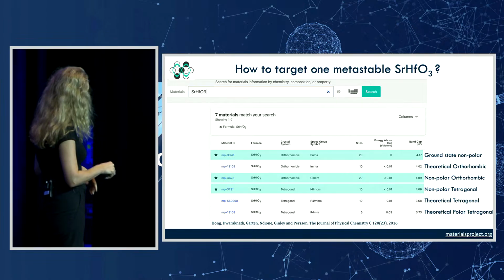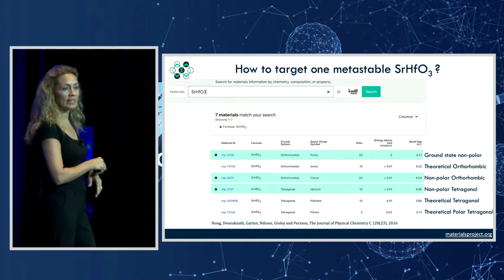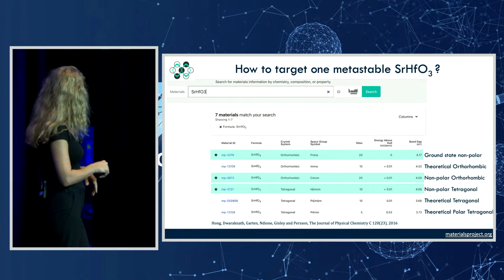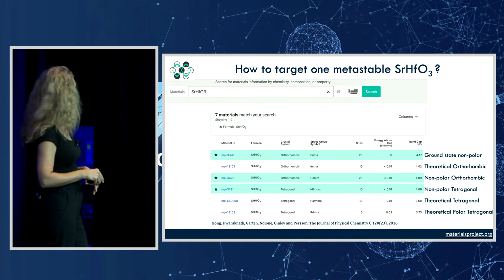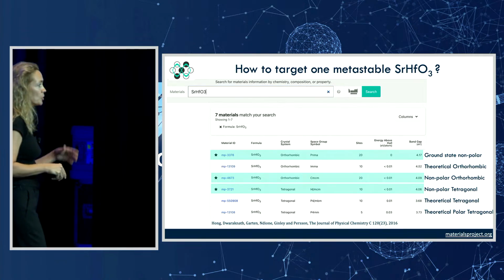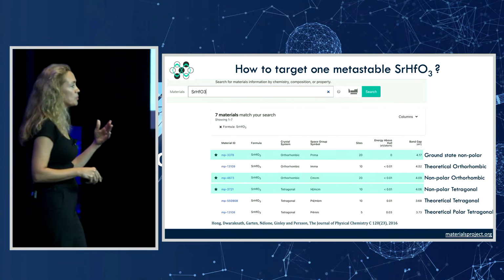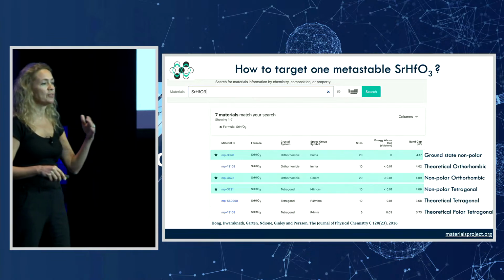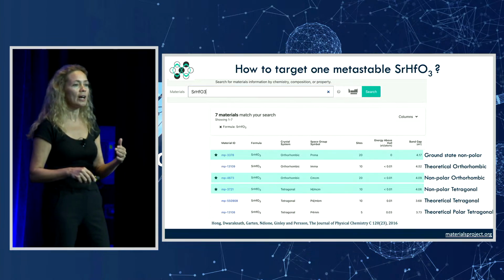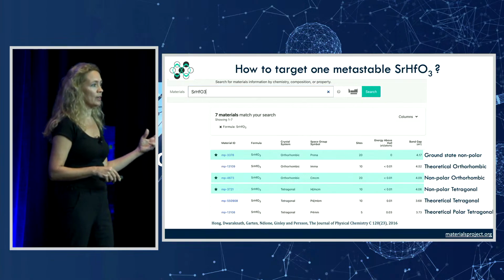It's the only one that's polar, the only one that's going to have a piezoelectric response, and it's number 1, 2, 3, 4, 5, 6 in order in terms of stability. It's 30 meV above the hull, which in itself is not a bad number, but the fact that it competes with 500 materials, 3 of which already have been made, is very bad news indeed.